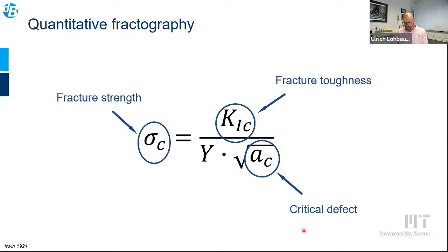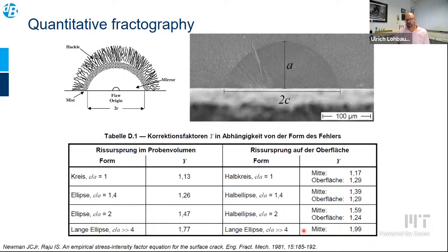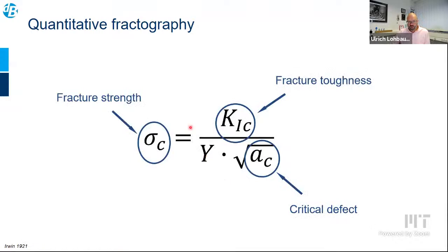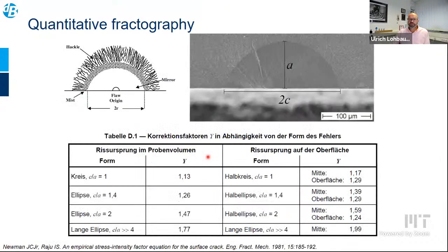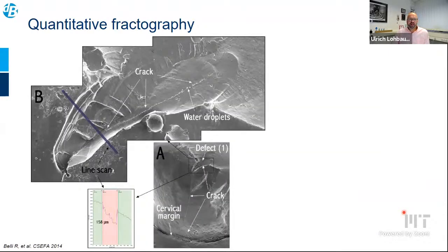So this is very common for all of us as mechanical engineers, of course, but we can use it in fractography. We can measure a defect at a surface or an internal defect. And we can say there is a shape factor, the Y. Here is the Y, sorry, I haven't mentioned that. Geometric factor is the Y. And this has a different geometric shape for a different ratio of extension C to depth A. So we need to adjust and see on a fractured surface how we categorize our fracture origin.